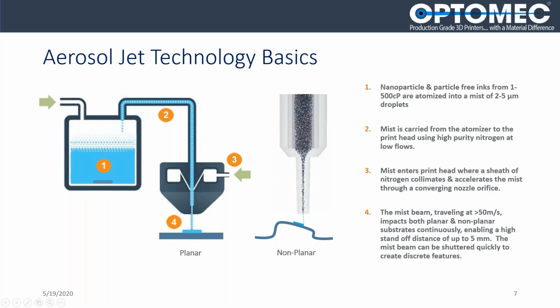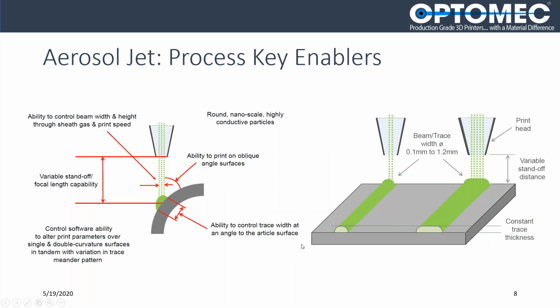And this allows us to be 1 to 5 millimeters off the surface of the part and print onto some oblique surfaces, which we'll show here. So this is kind of the key enablement of the Aerosol Jet technology, the ability to scale the line width and to print onto non-planar surfaces and get consistent trace thickness as you traverse the print head around the substrate.